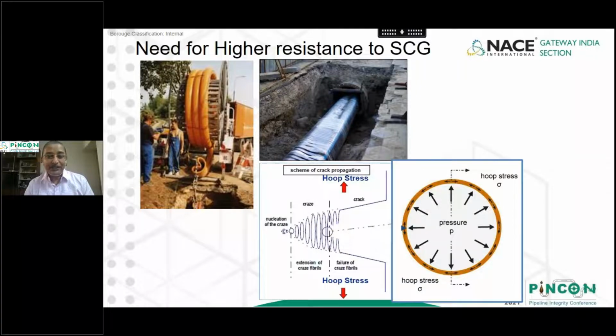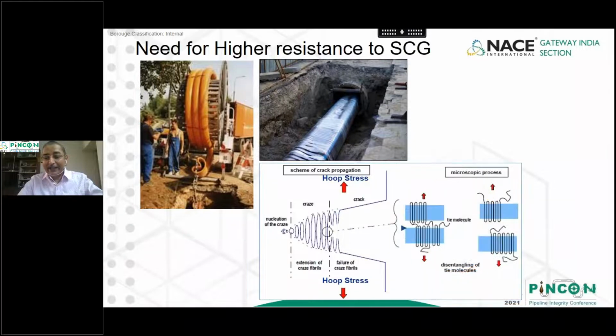Now, while doing these operations, there can be a lot of notches and scratches on the pipe, and the pipe should still provide 50 years service life despite these notches and scratches. When a polyethylene pipe has a notch, it starts opening up like when you cut a textile and the threads keep opening up. In a similar way, slowly the polyethylene molecules get disentangled. And here you can see that if you have more tie molecules between the crystalline zones to hold them together, this failure can be delayed a lot.